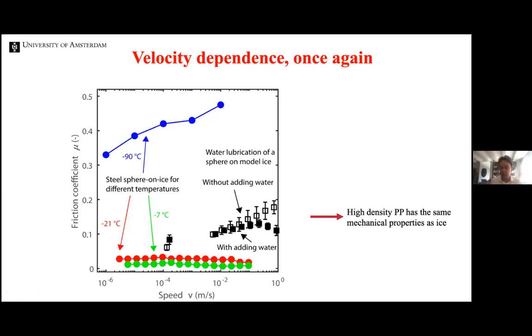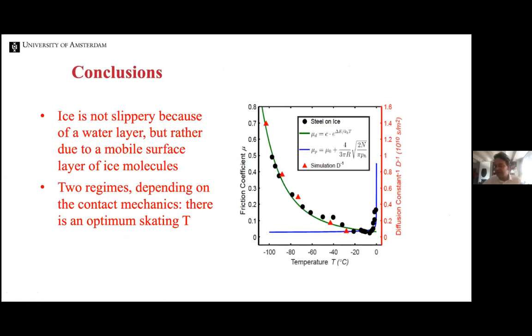skating is possible. And you already knew that, of course, because if I would pour some water on your kitchen floor, which also could have similar properties as ice, it's impossible for you to skate on that. And so the conclusion is that ice is not slippery because of a water layer, but rather because of the existence of a mobile surface layer of ice molecules. And I stress that these are ice molecules and not water molecules, because the simulations clearly show that their position is always within the crystalline lattice, even though they are very mobile.